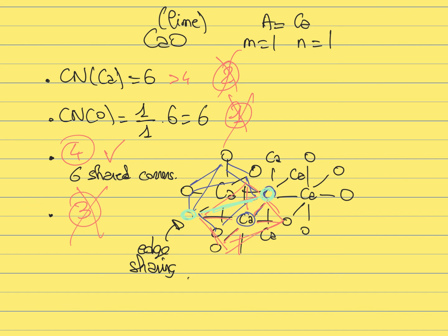So by simply checking those 4 rules, you can check if the connectivity is high enough but not too high. You want this sweet spot of connectivity where the glass is rigid enough to form a 3D network, but also flexible enough to form a disordered structure. This is what is checked by those 4 Zachariasen rules.